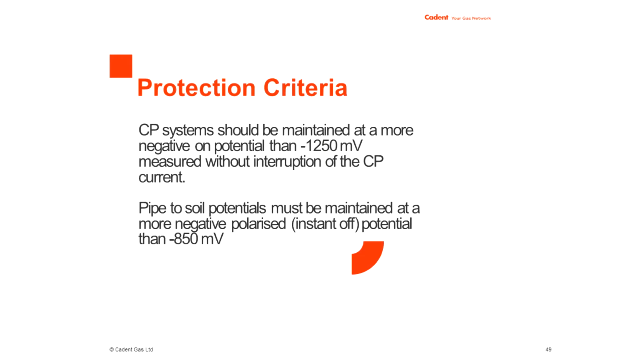What we're trying to achieve at these test posts is a reading of minus 1250 millivolts. When we see that, we know that the pipeline is adequately protected, as it has been researched over a number of years. However, that reading has an error in it. The error is caused by the distance between the pipe and the top of the soil, and it's known as an IR error. So to achieve the optimal level of protection, what we need to be aiming for is minus 850 millivolts, but this is at the instant that the current is switched off.